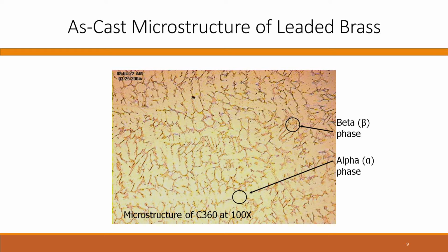When you add zinc to copper and you cast in these either vertical or horizontal continuous casting operations, your microstructure is pretty coarse. What you see in the light yellow area is what's called alpha phase, and that's 35% zinc, 65% copper, uniform mix. And then you've got this slightly darker stuff in there. It's called beta phase, and that's 45% zinc and 55% copper. And during casting, that just forms naturally.